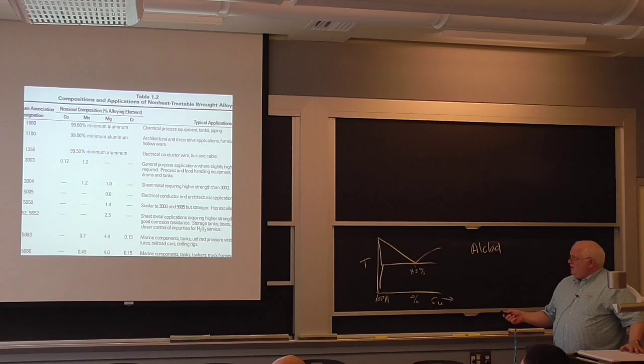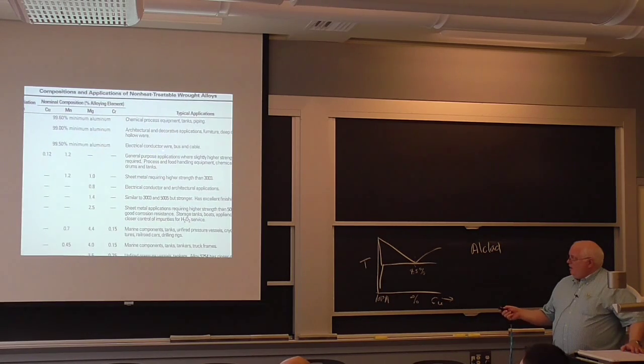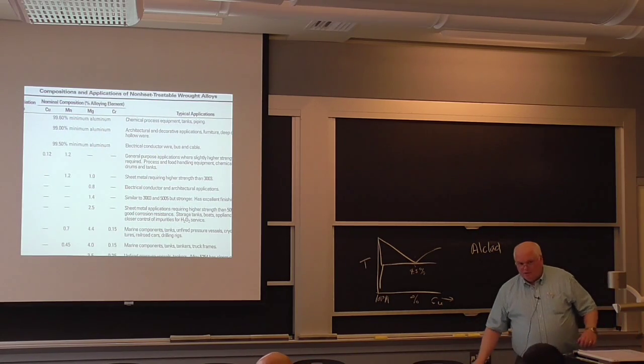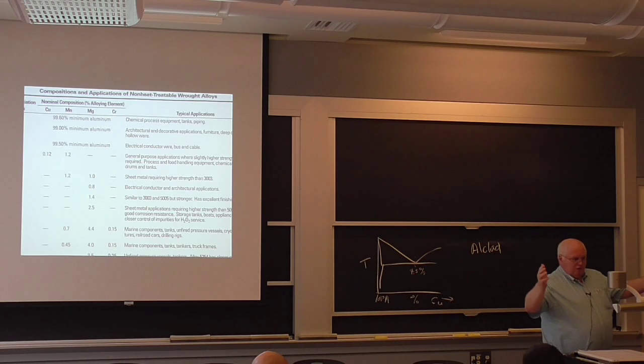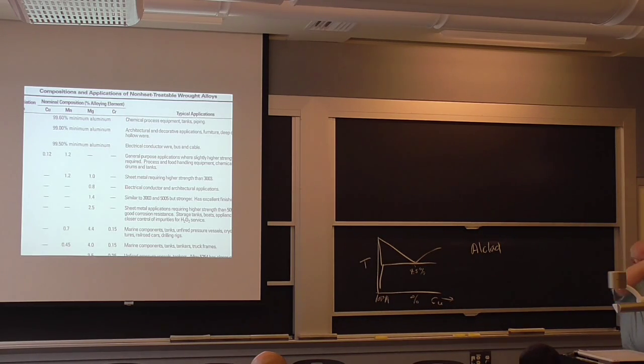1350 is 99.5% aluminum, an electrical conductor. So you see these 350,000 volt transmission towers, and you see the cable strung in between. It's aluminum. But guess what? It's got a steel core for strength. Aluminum for electrical conductivity, not thermal conductivity. Well, electrical and thermal conductivity go together with metals.